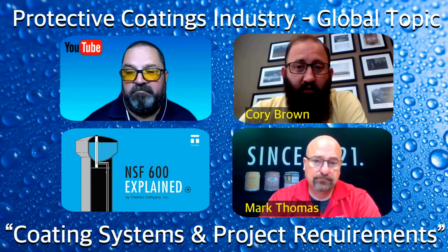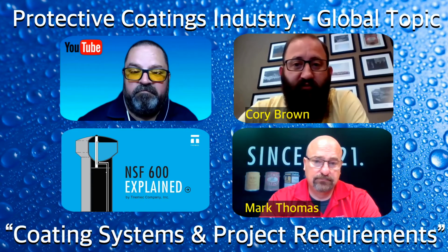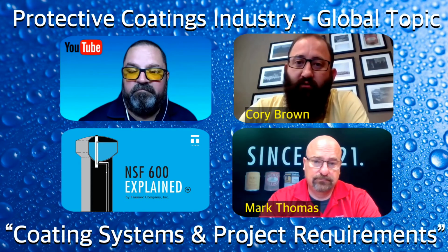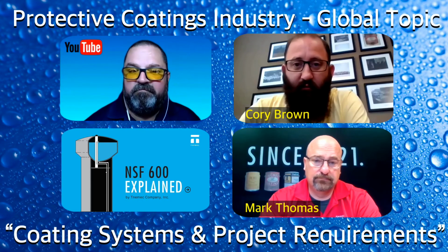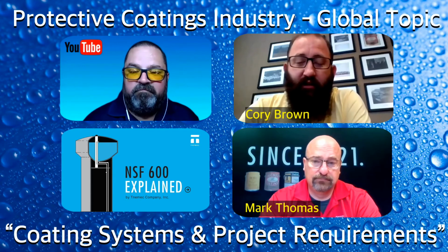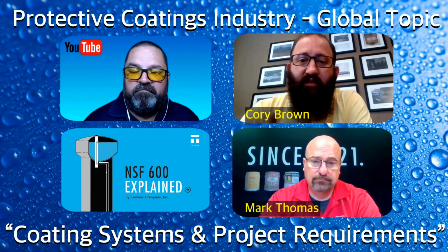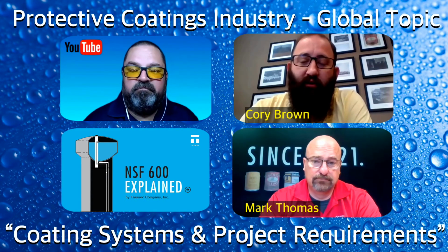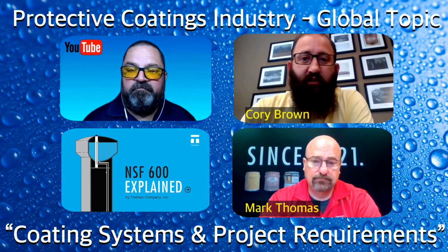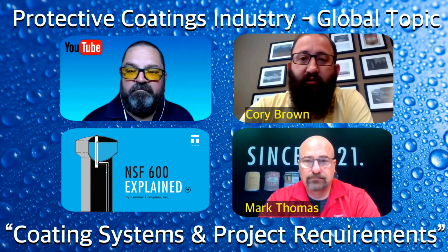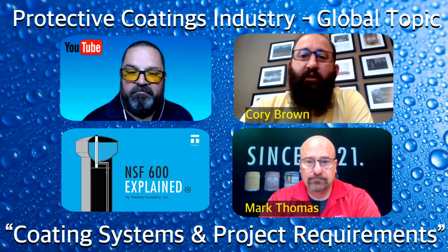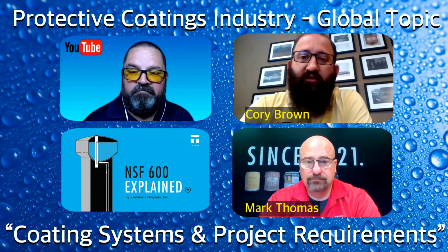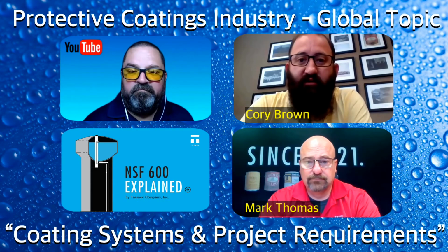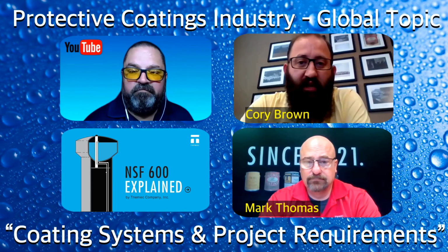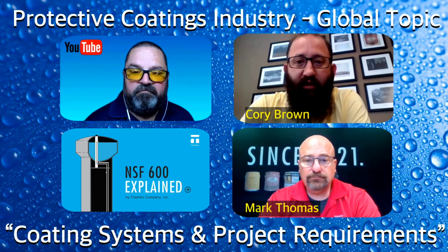So as far as field inspection goes, I think it's critical to specification writers that you include SSPC's PA2 as part of the field quality control assurance. That's an old standard method that SSPC developed for determining the average thickness of a field applied coating. It is incredibly useful in these situations because it takes square footage into account. If a field applicator, as they sometimes do, exceeds the specified thickness by a few mils, we can calculate the square footage that's affected. We know the volume of the tank, and then we can determine if we're still within the certified range based on that surface area to volume calculation. So PA2 is the standard that helps us bridge that gap. It's critical for specifiers to include that in their specifications.